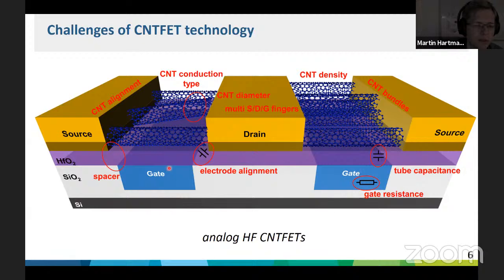So you need to have a quite precise alignment between those metal layers. But nevertheless, you also want to change the spacer in order to have control over your contact region. This can be beneficial, but just to a certain extent. And this is the main part of the research that we did quite recently. Another important aspect is that you need to think of a proper material for the gate. It should have a low resistance to reduce the overall gate resistance. And the question is also how many of these gate fingers to use in parallel to reduce the gate capacitances, the gate resistances. And then the last point that I would like to mention here is the CNT density.